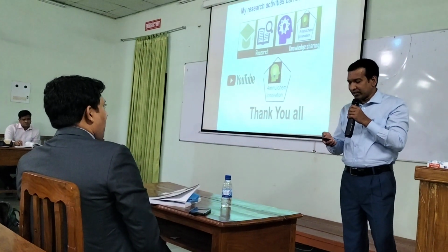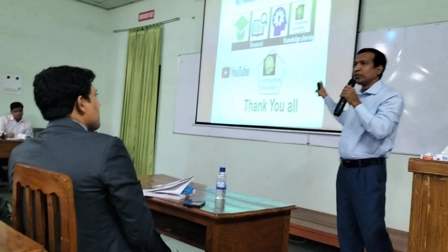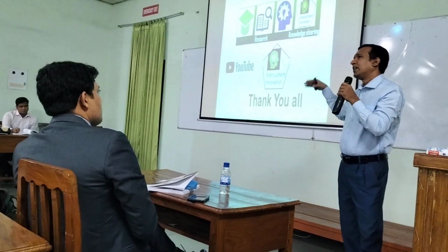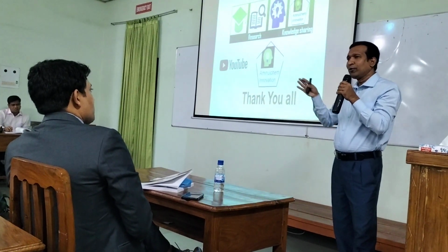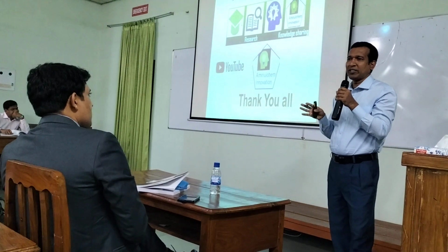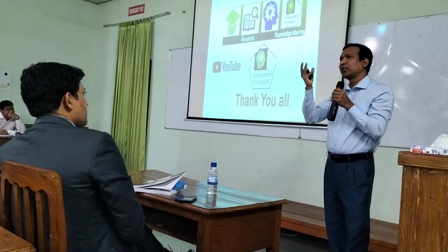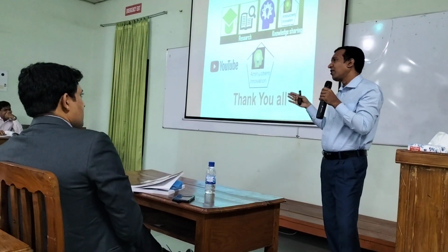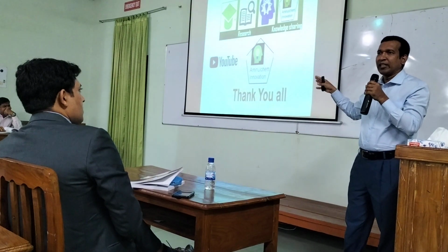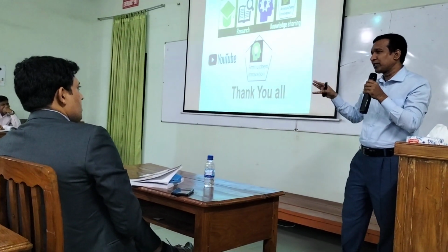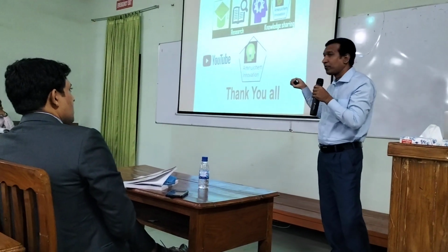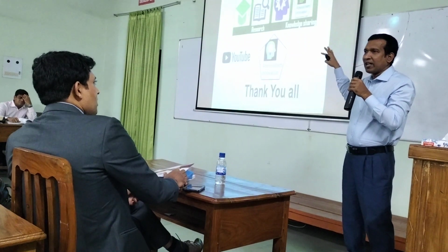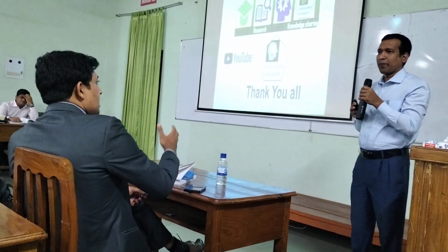Thank you so much for this interesting question. Actually, we have shown that the point of zero charge is 7.5. It means below 7.5, the surface is positively charged, which will attract negatively charged pollutants. On the other hand, beyond 7.5, the surface is negatively charged, which will attract positively charged pollutants. Here, for the case of methylene blue, we found that adsorption capacity is higher at higher pH due to surface charge.